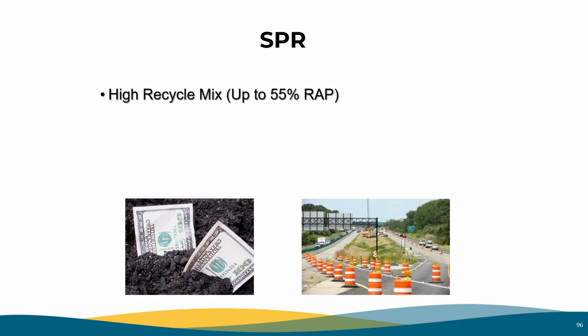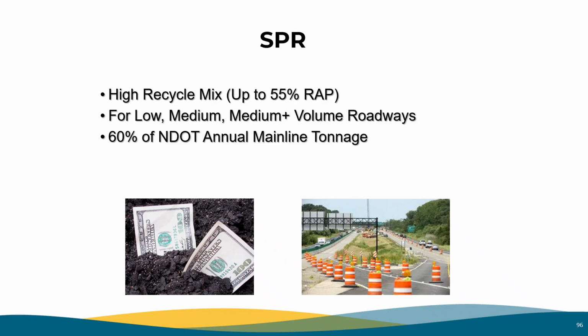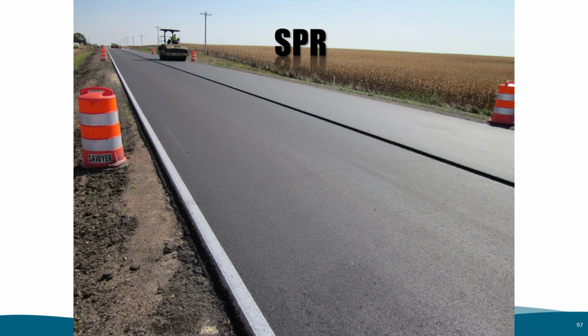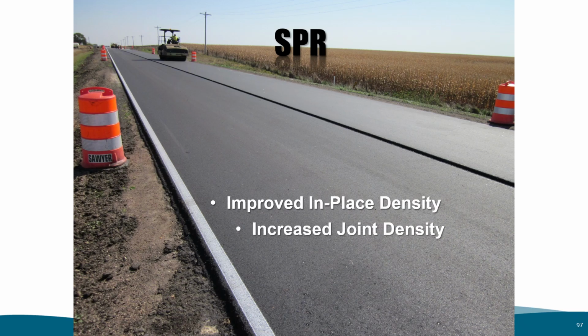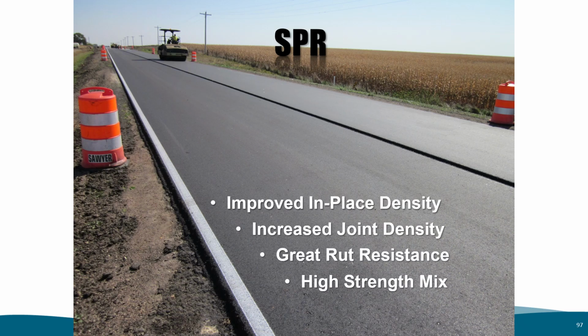It uses a high recycled mix, up to 55% RAP. It is used for low, medium to medium-high volume roadways. SPR accounts for approximately 60% of NDOT annual tonnage. SPR usage has improved in-place density, increased joint density, has better rut resistance, and increased structural value.